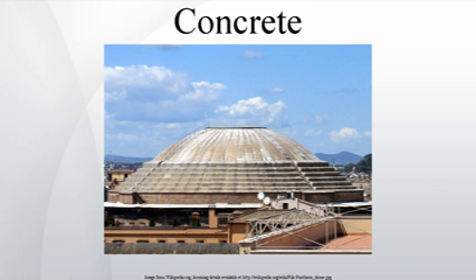Malapudi used the pulse velocity method to characterize the properties of concrete containing carbon nanofibers. The test results indicate that the compressive strength and percentage reduction in electrical resistance while loading concrete containing carbon nanofibers differ from those of plain concrete. A reasonable concentration of carbon nanofibers needs to be determined for use in concrete, which not only enhances compressive strength, but also improves the electrical properties required for strain monitoring, damage evaluation and self-health monitoring of concrete.